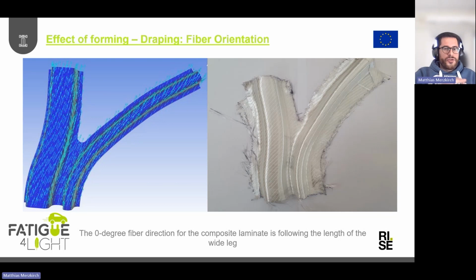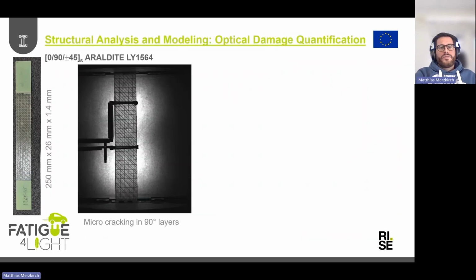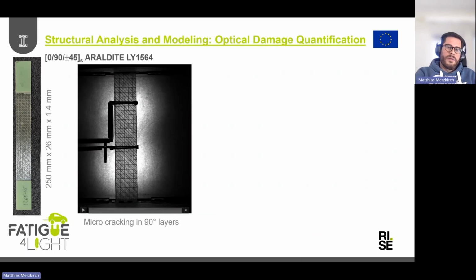So coming to the complex shape here, the aim was using a very simple draping simulation just to make sure that the final 0-degree fiber direction is along the composite, the wide leg of this lower control arm. Before we come to complex structures, we are understanding the coupon level. So specimens have been manufactured and some resin has been added to the fiber layup.